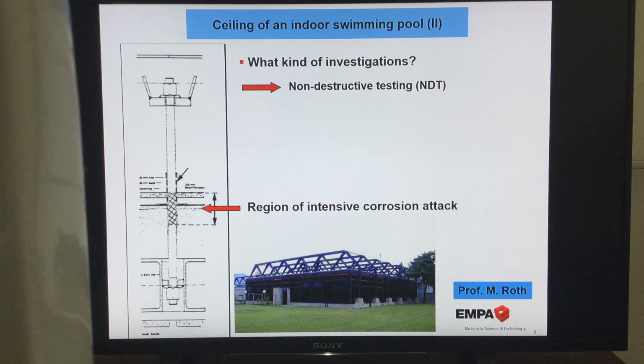So it's very important, then you have an idea of the whole component and not partially. The next step is also very important. Maybe there are some signs from non-destructive testing, some appearance of a crack there, or maybe also in this region, then we selected some of these steel hangers and we performed with them direct tensile tests.